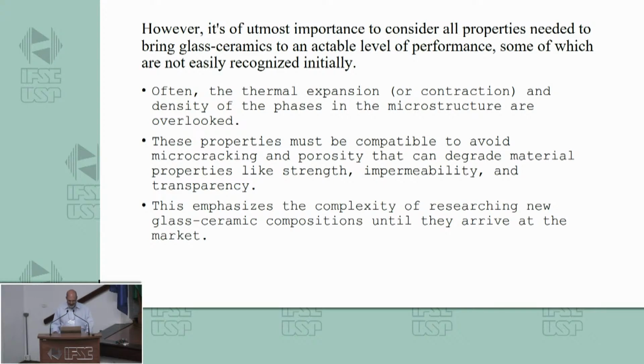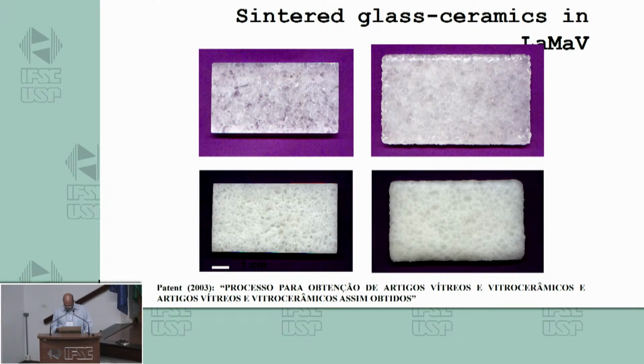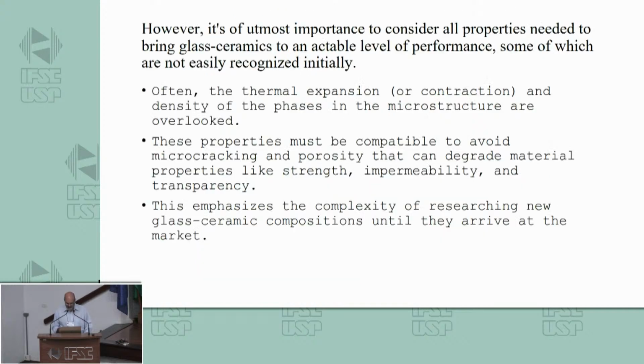For example, the thermal expansion coefficient of the phases present in the system have to be aligned so we don't have cracks in the system. They have to be compatible to avoid microcracking, and also the density of the present phases has to be managed to avoid the pores that appear when you have glass crystallizing in a confined residual glass.